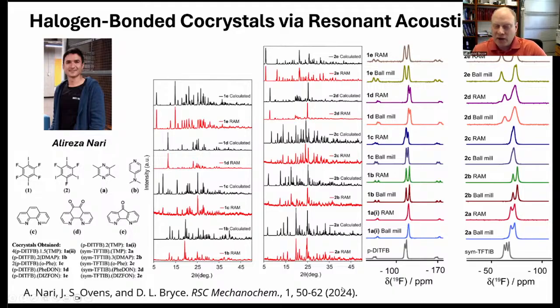And we have powder X-ray diffractograms here. So you can pick a couple and look by eye here, the calculated trace from the single crystal X-ray structure, and then what we're able to get with RAM. And in basically all of these cases, most of these cases, we get bang on what you would expect. We can also then, in this case, use fluorine-19 solid-state NMR. So those are the traces on the right-hand side, because our donor molecules 1 and 2 have fluorine nuclei in them.